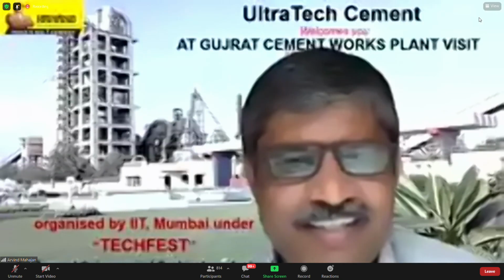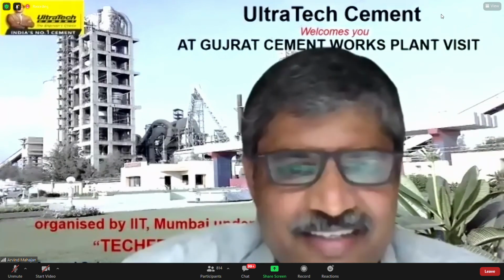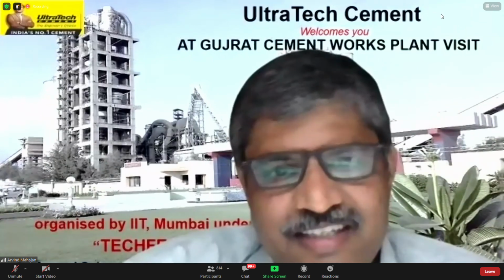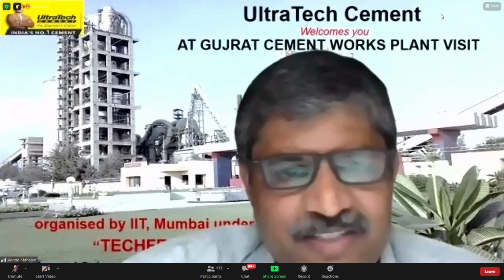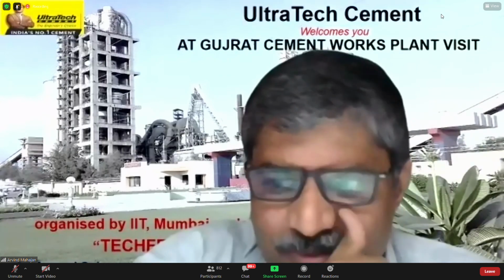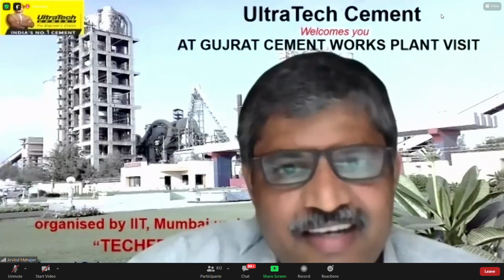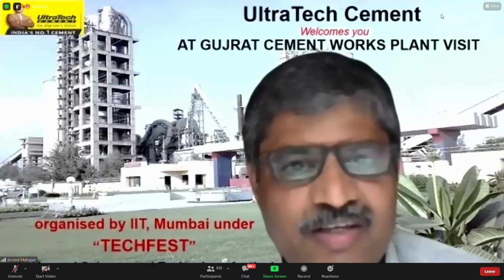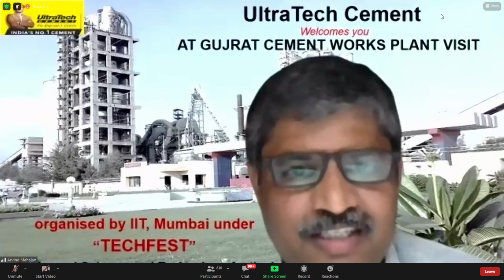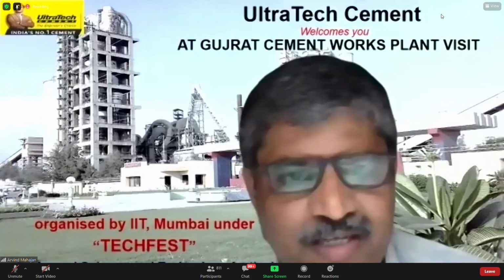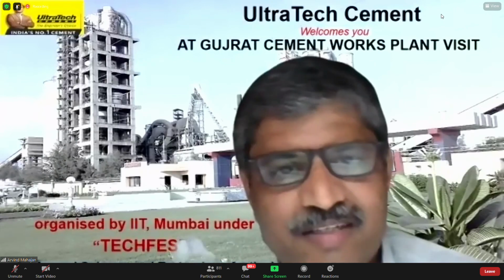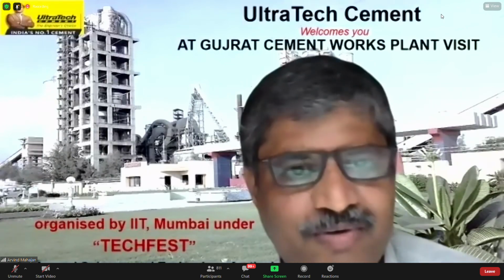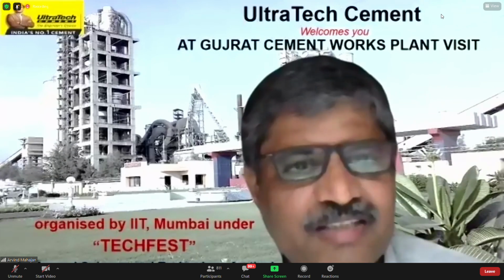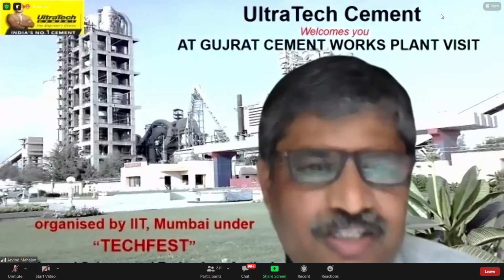So thank you, Sanjay ji. You have explained it very nicely. So actually, this question is not that relevant, because cement manufacturing plants are continuous process plants that never stop. It is not like you start from this location and you stop it and then again start and again stop it. It's a continuous plant. The plant capacity of our kiln, one single kiln in Gujarat Cement Works, is around 8,000 tons per day. So 8,000 per day means per hour it comes to 330 tons per hour. And for 1 minute, it is around 5.5 to 6 metric tons per minute.